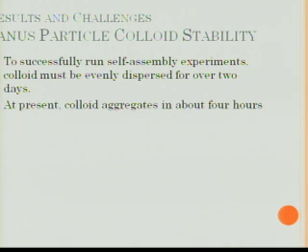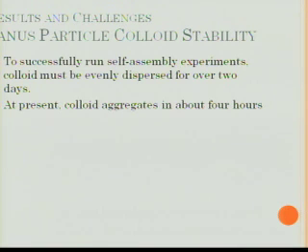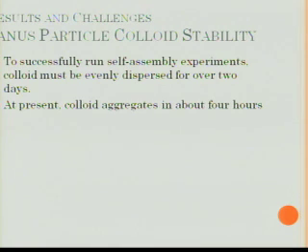As I said before, zeta potential is really important to colloid stability. So what's wrong with our colloids? In order to get really good self-assembly experiments, we need our colloid to be evenly dispersed throughout our solvent for over two days. At present, our colloid starts to clump together — all the particles mash together and settle down — and our colloid is destroyed in about four hours.